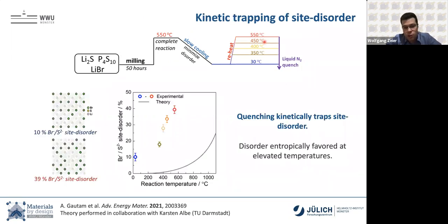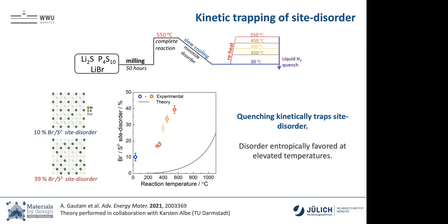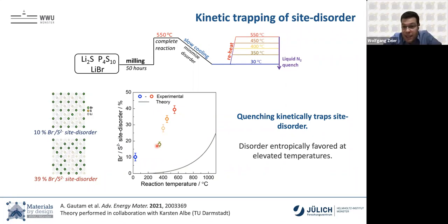So usually you would think nothing should happen, but a lot actually happens. And our site disorder is a direct function of our synthesis temperature. If you quench from 550, you're at 40%, and the lower your quenching temperature is, the lower you are in this order. At some point, nothing changes really, because if you quench a material from 100 Celsius, it's already in the state where it wants to be, because you still need thermal energy for ions to diffuse around and to swap sites. But again, I think the story here is that the quenching really traps the site disorder, and this disorder seems to be entropically favored at elevated temperatures.